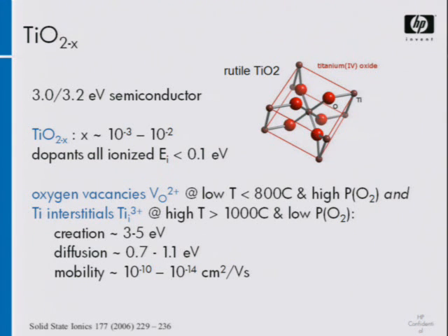And if you think about that, what you then have is actually a metal. You have something with such a high doping that it's really metallic in its nature. So you've got a material here in which it's possible to go through effectively a metal insulator transition by adding or removing vacancies from the system. These vacancies can diffuse in the material, but depending upon whether it's a single crystal or polycrystalline material, the diffusion of those vacancies is really very slow.